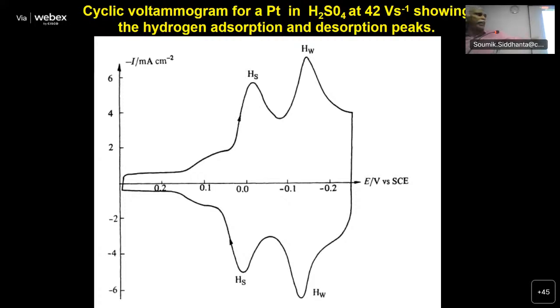If you ask in situ techniques, in operando techniques, you can understand. And if you calculate the area of this peak and the area of this peak, you can calculate how much hydrogen is adsorbed on this. And this is one way of measuring surface area of platinum. You have got platinum nanoparticles attached on this and record a voltammogram. From this, how many microcoulombs are necessary to get a monolayer, we can calculate. So the area of these peaks will allow you to calculate electrochemically accessible surface area, which is different from BET surface area.